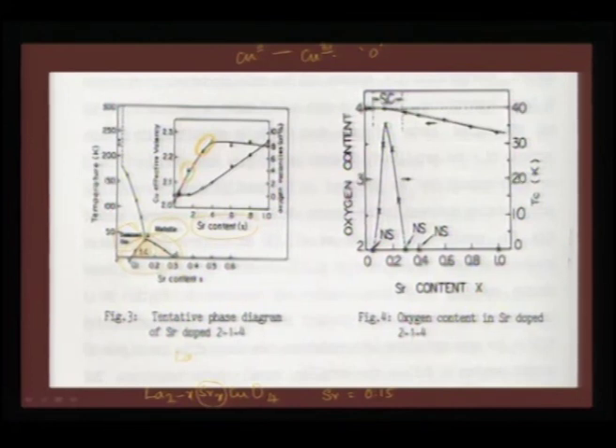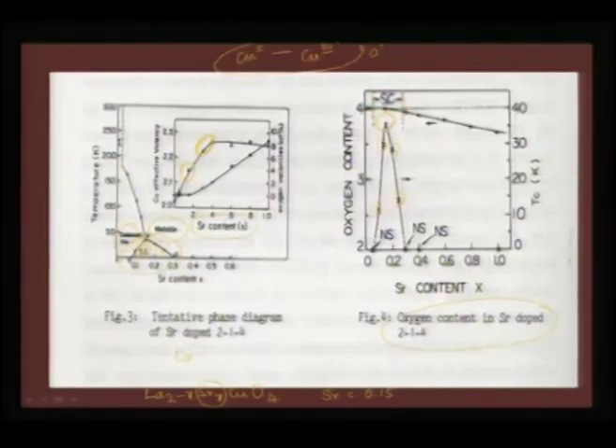Some of the copper gets oxidized to copper 3 plus, and this is another plot which tells about the oxygen content in strontium doped La2CuO4. You can see very well here that this is the superconducting region where the oxygen content is very close to 4 and the Tc is at its maxima. If you bring it down either way, then the Tc falls rapidly and it goes into a non superconducting state. So, the incorporation of oxygen in all these cuprates is very critical, and that also partially governs the oxidation state of copper, copper 2 and copper 3, which is affecting the copper in the copper oxygen chain, which is in the AB plane.